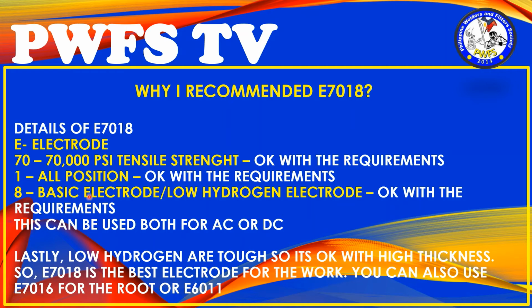8 is a basic electrode or low hydrogen electrode. Since you have a high thickness material, you will need a low hydrogen electrode. Thus 8 is a low hydrogen electrode. So all the details of E7018 meet the requirements for welding, right? And another thing, E7018 is for both AC or DC. Since you have a DC welding machine, E7018 is also okay. Lastly, low hydrogen electrodes are tough, so it's okay with high thickness. So E7018 is the best electrode for the work.